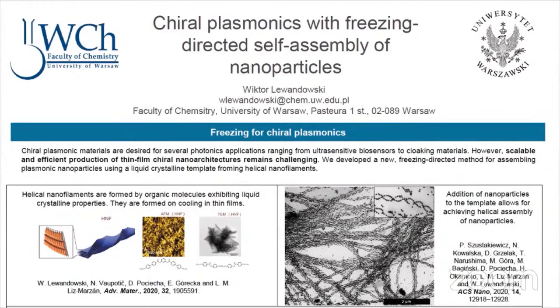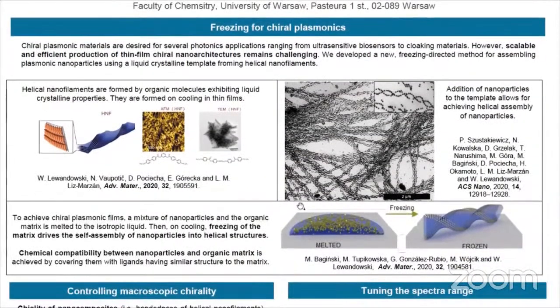We summarized the recent progress in one of our review papers. But then, if chemically compatible nanoparticles are added to the organic matrix, these nanoparticles tend to be well dispersed in the isotropic phase at elevated temperature. However, on freezing, they locate selectively on the edges of helices, producing chiral plasmonic assemblies.